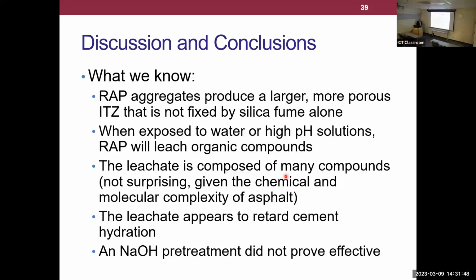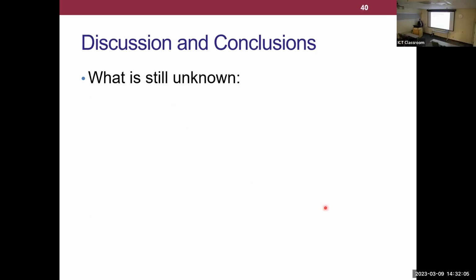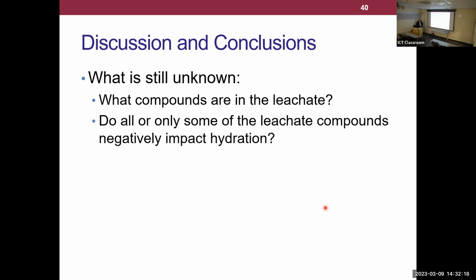And then we also showed that sodium hydroxide solution to try and pre-leach the organic compounds did not appear to be very effective. A very marginal increase in strength. And then we saw much larger organic compound content in the leachate. So what don't we know? We don't know what that leachate is. We know it's a whole bunch of compounds. We know there's a whole bunch of functional groups. All those functional groups are just organic compounds. Doesn't really help us.